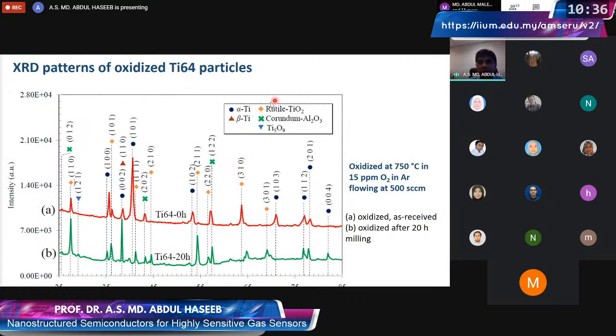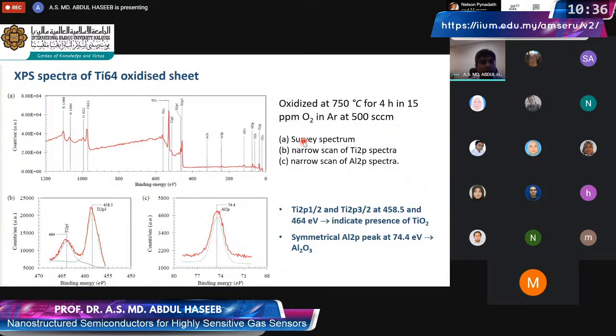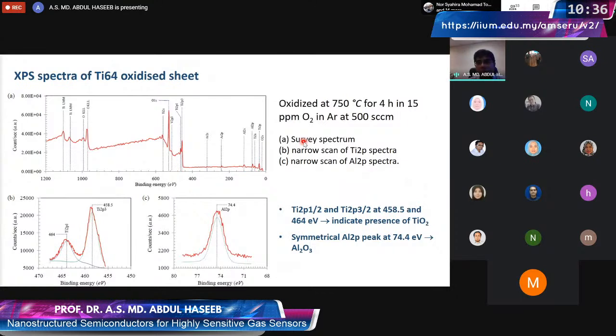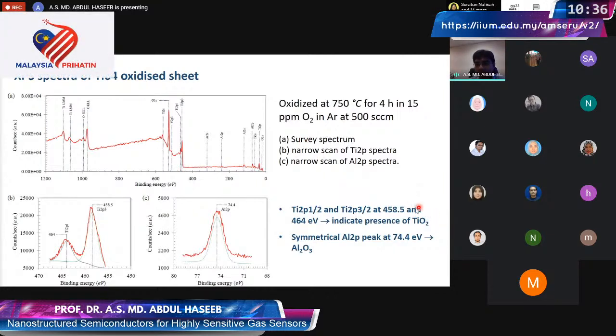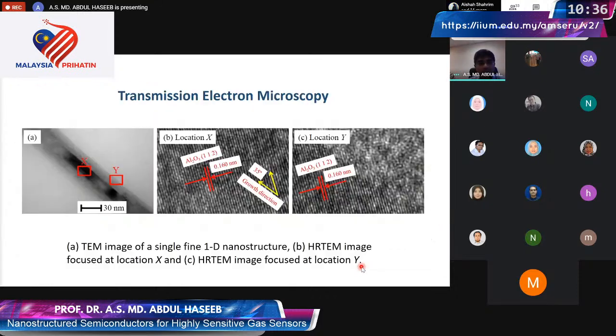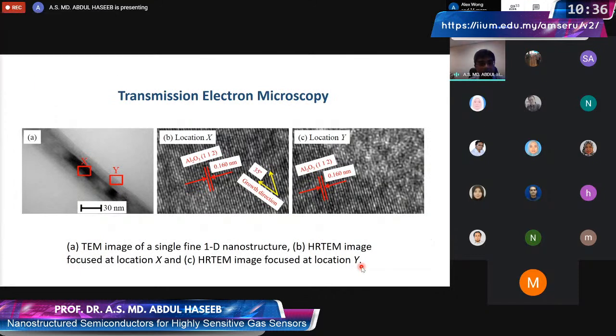In addition to the stoichiometric rutile, we also get some sub-stoichiometric oxides as well, in small amounts though. XPS was used to confirm the chemical nature of those oxides. And indeed, we found that we have this titanium oxide and also aluminum oxide, from the binding energy calculation. We have done the transmission electron microscopy.